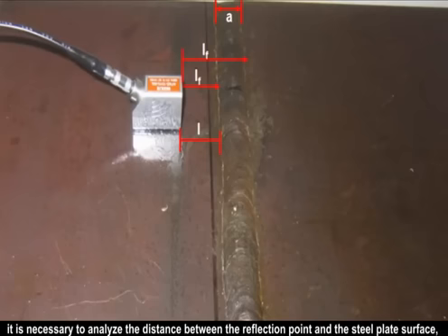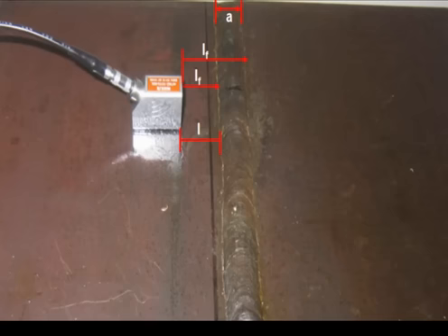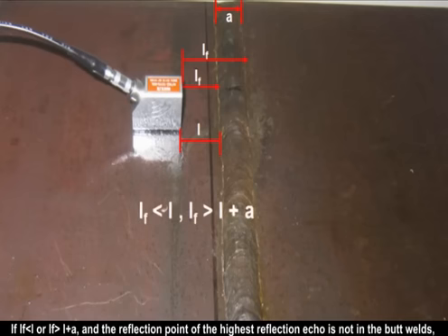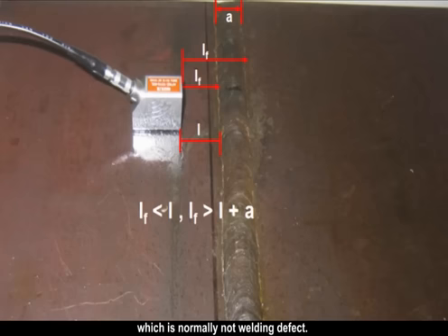If using the second echo, it is necessary to analyze the distance between the reflection point and the steel plate surface and the weld groove type, and then judge whether it is defect reflection. If LF is less than L, or LF is greater than L plus A, the reflection point of the highest reflection echo is not in the butt welds, which is normally not a welding defect.